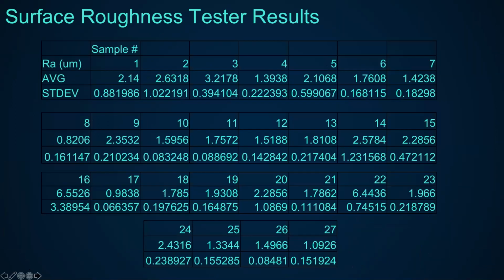These are our results that we concluded. If you scan through, you can see that run 8 came in with the lowest at 0.8206. And again, one of our rougher samples that we tested was run 6 with 1.7608. Next slide, please.